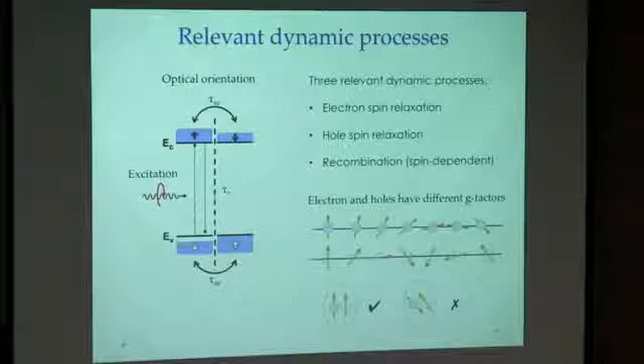After precession for some time, for exciton states with a total angular momentum of 1, recombination is allowed and gives out a circularly polarized photon. But a total angular momentum of 0 is not allowed. That recombination is not allowed. In our measurements, we haven't really measured anything related to recombination because the recombination time is much longer. We are dominated by spin dynamics of the excitons.